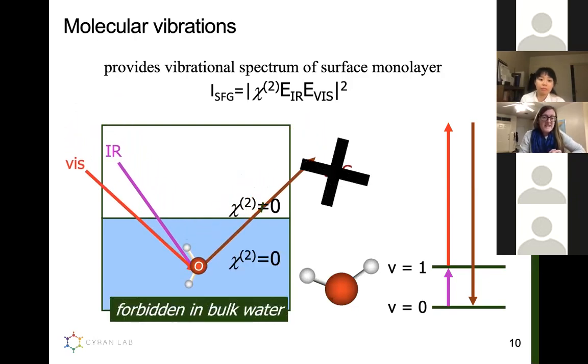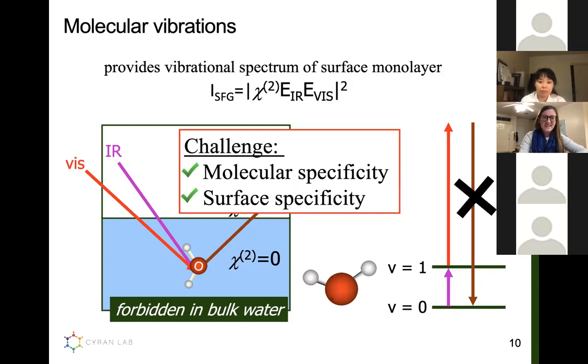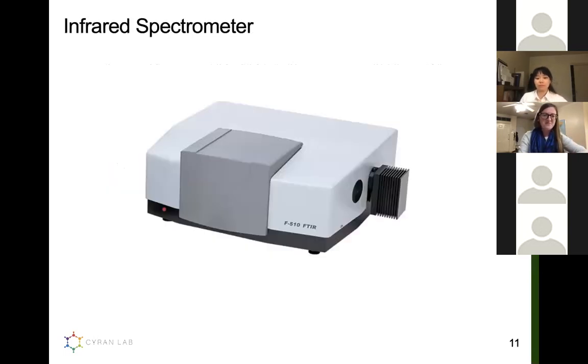In the bulk, this SFG signal is prohibited, or forbidden. And so you do not generate an SFG signal within a bulk solution. And so in this way, we can eliminate the contributions from the bulk and only look specifically at a surface. And more specifically, we can look at only a monolayer of water molecules that are interacting at a surface. And so this is how we get both our molecular specificity in terms of vibrational spectroscopy and surface specificity by using sum frequency generation spectroscopy.